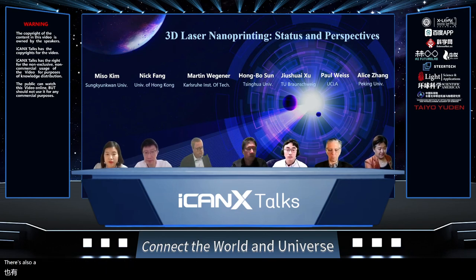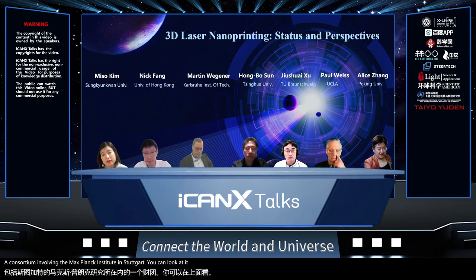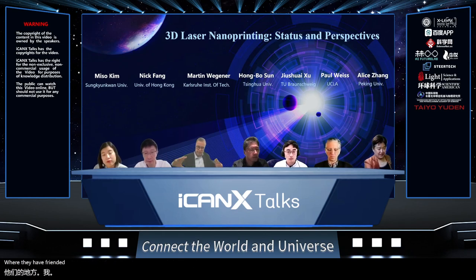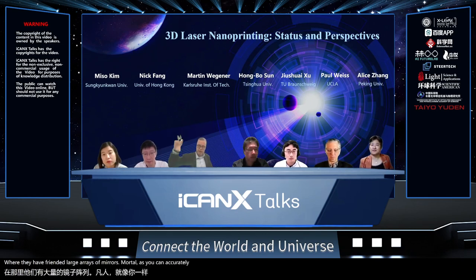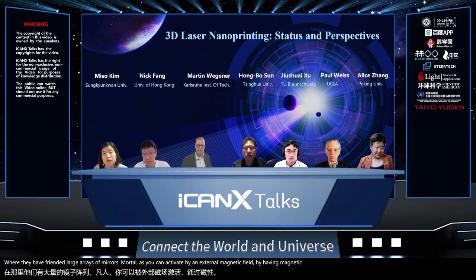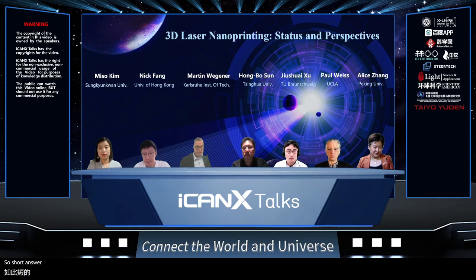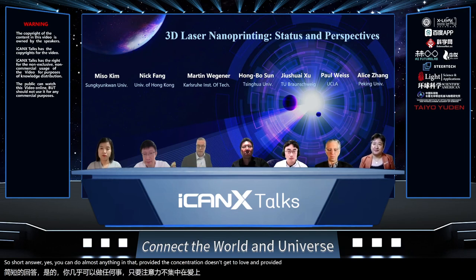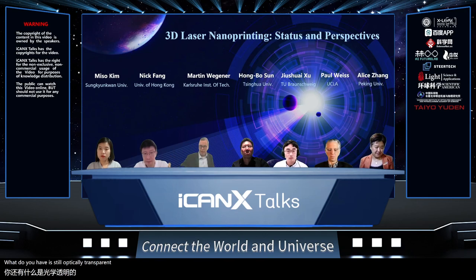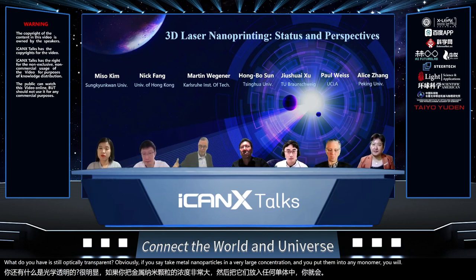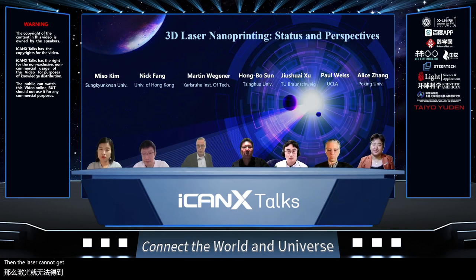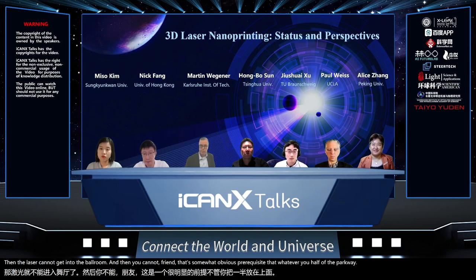There's also a nice recent example by a consortium involving the Max Planck Institute in Stuttgart. You can look at it also on the Nanoscribe website, where they have printed large arrays of little motors you can activate by an external magnetic field by having magnetic nanoparticles inside of the polymer. So short answer, yes, you can dope almost anything in there, provided the concentration doesn't get too large and provided what you have is still optically transparent. Obviously, if you take metal nanoparticles in a very large concentration and you put them into any monomer, you will get something that looks opaque, and then the laser cannot get into the volume, and then you cannot print. That's a somewhat obvious prerequisite that whatever you have is halfway transparent to the light you are using.